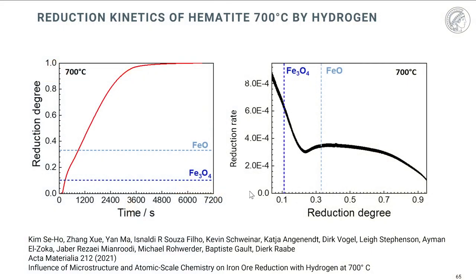Here we have the kinetics at 700 degrees centigrade under hydrogen atmosphere. First, you see the very fast reaction rate from hematite to magnetite and from magnetite further to wüstite. But as soon as you get into the wüstite reduction state, and the wüstite is of course then further reduced towards iron, you see that the reaction becomes very, very sluggish and becomes slower and slower as you go along.